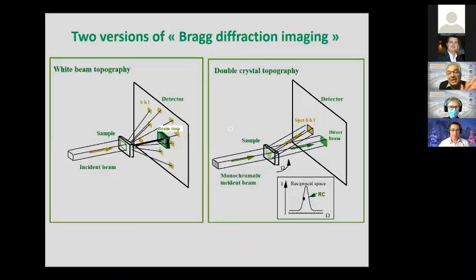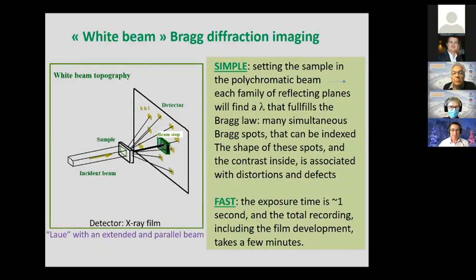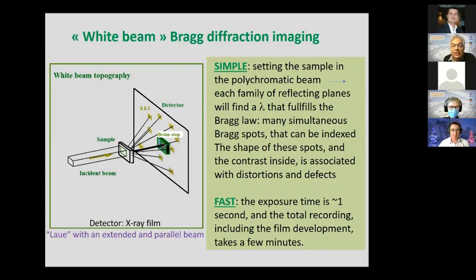You have two versions of Bragg diffraction imaging at the synchrotron. One is very simple, it's called white beam topography, and the other one is double crystal topography using a monochromatic beam. Well, let's start with white beam diffraction imaging. In white beam diffraction imaging, you set the sample in the polychromatic beam, and each family of reflecting planes in the crystal will find a lambda that fulfills the Bragg law. So you have many simultaneous Bragg spots you can record on your detector. And the detector needs to be big and also have a good resolution. And presently, the only detector that fulfills these requirements is X-ray film. So for this technique, we still use X-ray film.